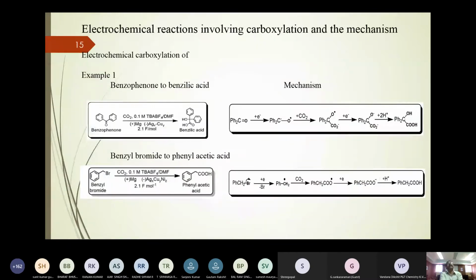Okay. Now I am showing two simple examples involving carboxylation as the mechanism. First one is benzophenone to benzilic acid. We all know about benzophenone, where we use carbon dioxide and tetrabutyl ammonium fluoroborate as the supporting electrolyte, dissolved in dimethyl formamide. Here we use a magnesium anode plus, for example, a silver copper alloy nano electrode, and we pass 2 Faraday per mole, and we get benzilic acid.